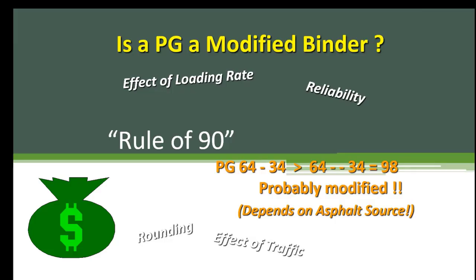So I mentioned modified binders. How do we get there? Well, rule of thumb, if you add those two numbers together, the absolute value of those two numbers, and they're getting around 90, and particularly if they're very far above 90, neat asphalt has to be modified, some type of modifier to get that type of temperature range. So when you start seeing a pretty big range between that high temperature and low temperature number, you probably have a modified asphalt.